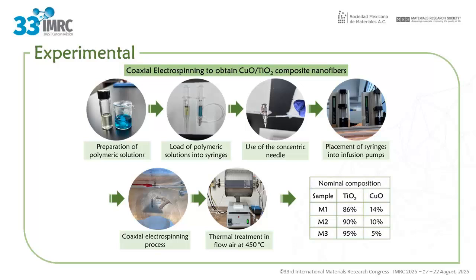Once both solutions were ready, they were placed in the separate syringes connected to the concentric needles, which in turn were attached to the infusion pumps and the high voltage power supply. The collector was positioned below the needles and also connected to the power supply. Electrospinning was carried out by applying 50 kilovolts with a fixed outer flow rate of 0.3 milliliters per hour and an inner flow rate that varied between 0.3, 0.2, and 0.1 milliliters per hour in order to obtain 3 different compositions. Afterwards, the fibers were calcined at 450 degrees Celsius for 3 hours to remove the PVP and obtain the crystalline phases of the oxides.